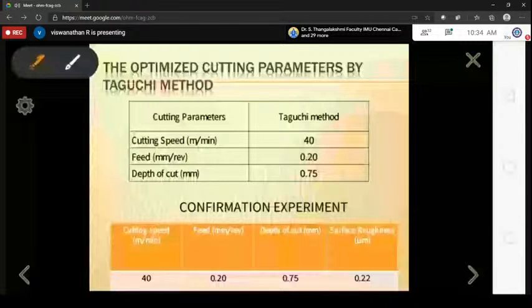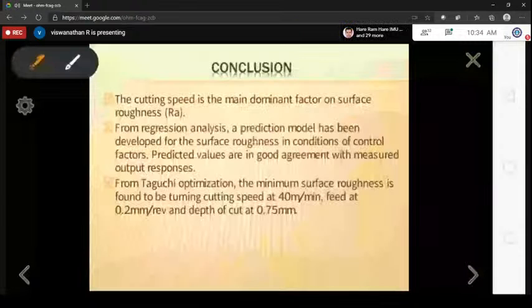The main conclusion of this work is that cutting speed is the main dominant factor on the surface roughness, compared to the feed rate and the depth of cut. Also, from the regression analysis, a prediction model was developed for the roughness, and the predicted value has good agreement with the measured output responses. The optimal cutting parameters are 40 meters per minute cutting speed, feed rate 0.2 mm per revolution, and depth of cut 0.75 mm.